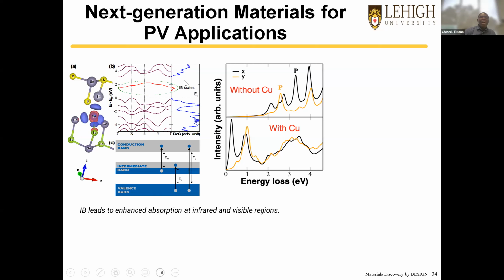We also did a high-level exciton spectral analysis of this material. And what we are showing here is this intermediate band gap, which shows sp3-like hybridization between the low-lying chalcogen sulfur atoms that are within the proximity of the copper.